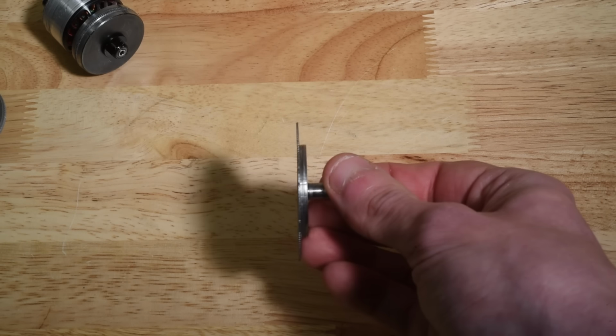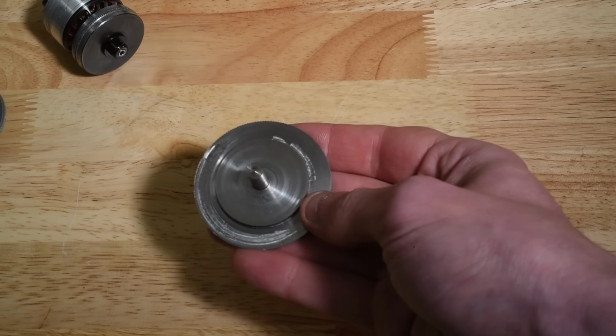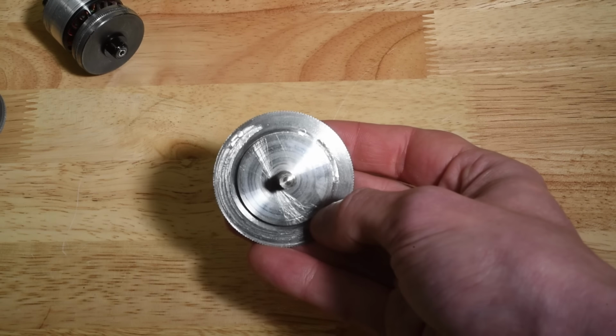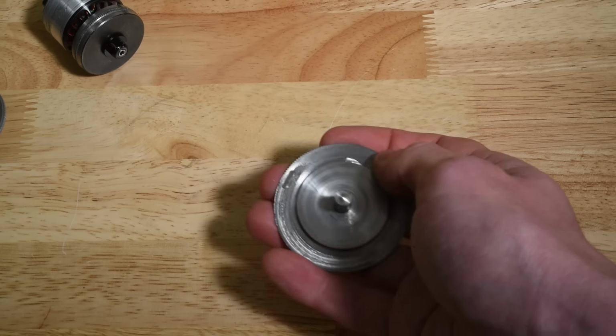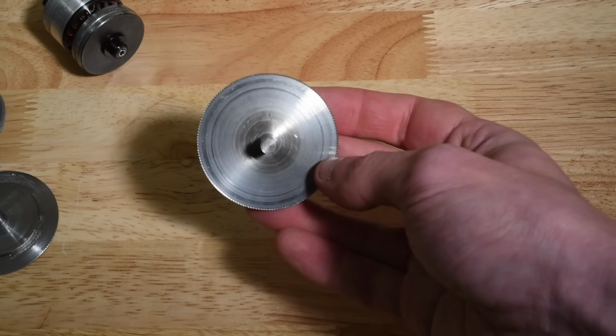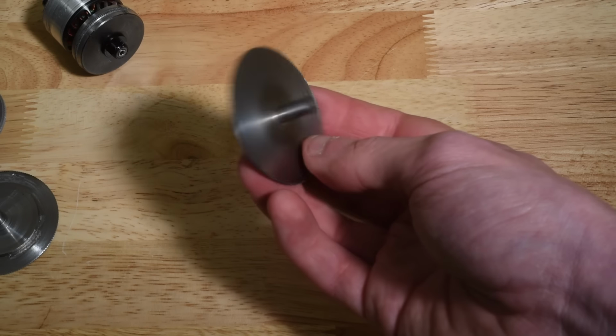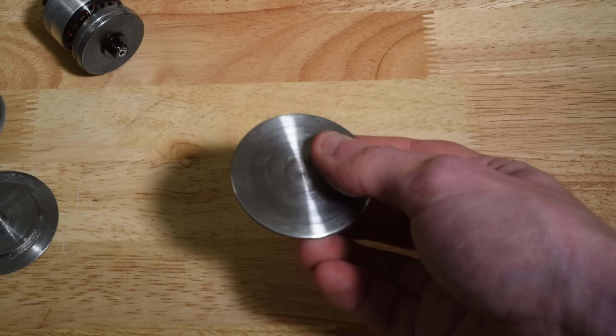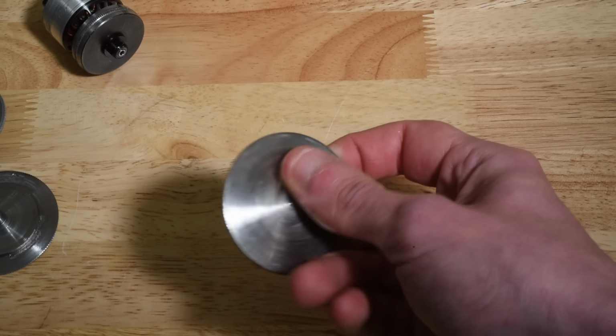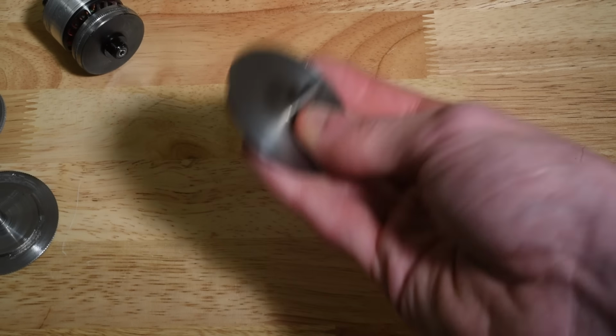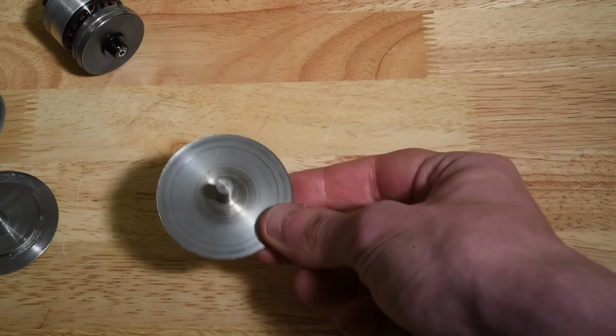And if you don't want to make it to its final thickness on the lathe, well, you're going to have to machine it in post, and that tends to remove even more material and cause it to be unbalanced. We even went as far as turning it all the way down, trying to remove all the excess material, but these end up being too thin and too flexible because they aren't hardened yet, which H13 requires in order to reach its full strength and stiffness.